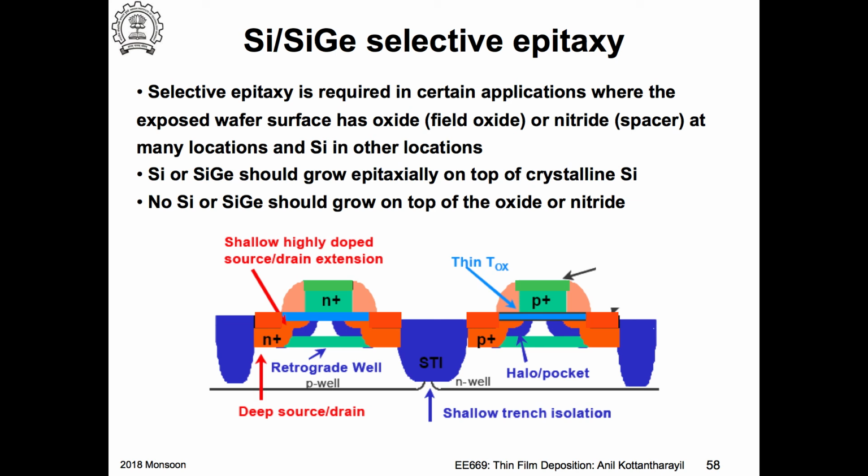What is he saying? Yeah, okay, so you are trying to etch silicon. Do you want to etch all the silicon that is deposited there? Only the polysilicon. Yeah, I want to deposit monocrystalline on monocrystalline silicon, but wherever polycrystalline gets deposited, I will add something which will etch the polycrystalline silicon. But do you think it will not etch monocrystalline silicon?